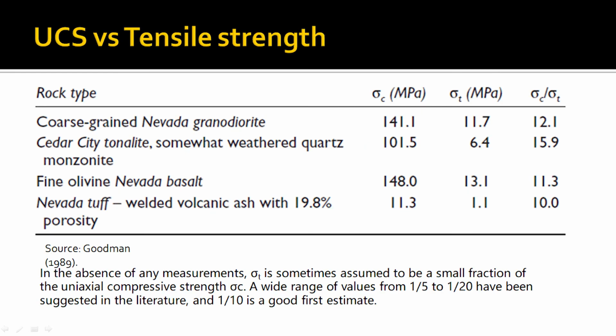Now these are the different UCS values and tensile strength values for different rocks that have been tested by Goodman. You can see the ratio between UCS for granodiorite and for volcanic ash. So in this data, the ratio of UCS by tensile strength ranges between 10 to 15.9. So you can expect that the disparity between UCS and tensile strength can go as much as 10 times to 15 times. But a good estimate that is generally used during the preliminary stage of design is 1/10, or between 1/8 and 1/12. So if you have a UCS of 10 MPa, you can safely assume that the tensile strength should be around 1 MPa.